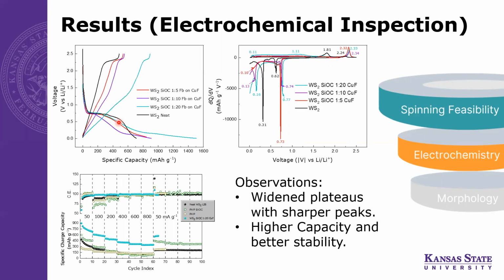Specifically, the conversion reaction and the SEI layer formation peak intensified for the higher mass ratio, and the peak for the intercalation reaction also intensified, which you can see at the lower voltage of the discharge curve and the higher voltage of the charge curve, respectively.